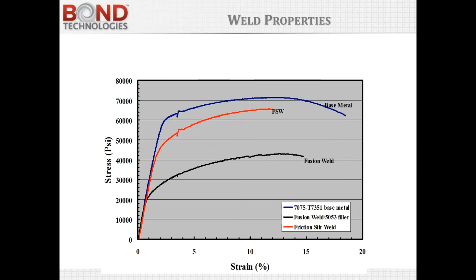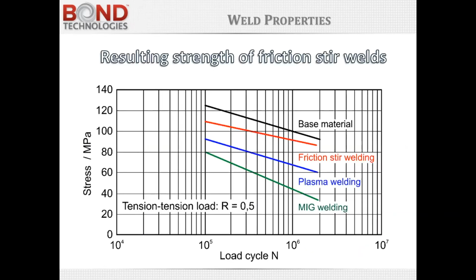This chart compares stress strain curves for fusion welding and friction stir welding for the base metal. In this example, it's a 7000 series T7351 material. But in most cases, like 7075, a stir welded joint does have superior joint strength to a fusion welded joint. In fatigue, friction stir welding also demonstrates superior performance to other welding methods. So the benefit from an application perspective is that if the welded joint is the weakest link in the structure, friction stir welding gives you the ability to reduce the thickness of the material, and it allows you to lightweight the product.